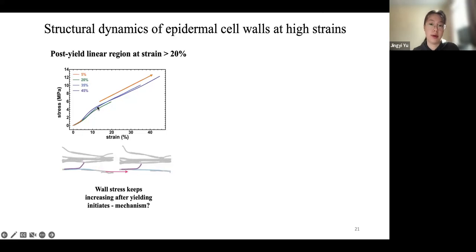However, our understanding of how the cell wall polymers rearrange themselves upon very extensive loading beyond 20% is still not well understood. One conundrum we were having here is that, based on our observation, we think the sliding event is a very important mechanism for plastic deformation. One would think that once the fibers start to slide, the contact area between fibers would become smaller and smaller, which means it should be easier to further stretch the cell wall, meaning less stress needs to be applied on the wall to induce further plastic deformation.